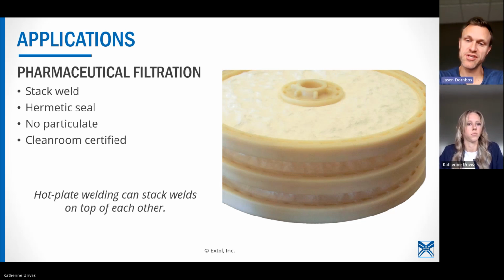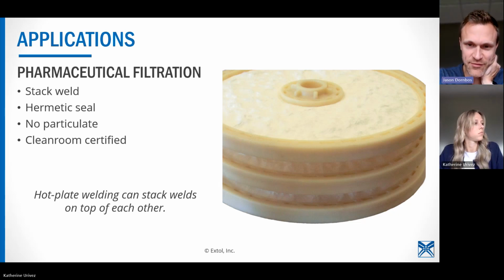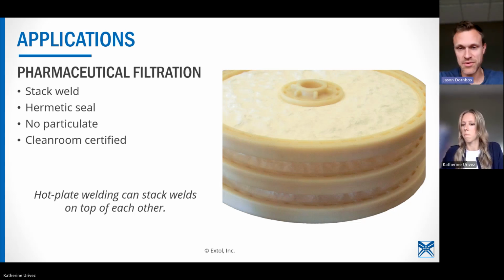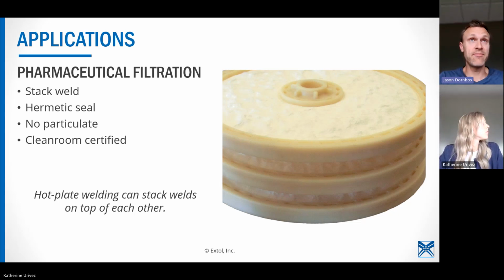Pharmaceutical filtration. So the first line there, stack weld. The component that you see there is actually welded 1, 2, 3, 4 times, and there's multiple layers. The way that you can do that is you stack parts on top of each other. So you do the first weld, and then you add the next layer, weld it, add the next layer, weld it. And we've done some for pharmaceuticals. Other industries are utilizing this as well.